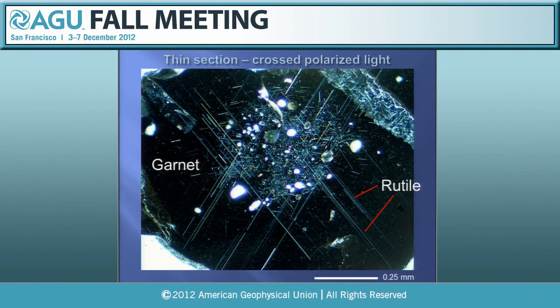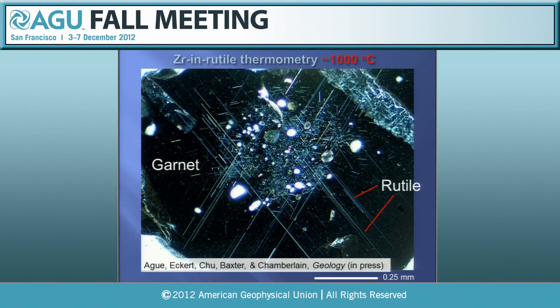Okay, it's known from experimental work that high titanium garnets really only form at very high temperatures and/or very high pressures, and the implication here is that these are precipitates that formed from the cooling garnet as the rocks were being exhumed. Okay, so if you do zirconium in rutile thermometry on these, we've used the Tompkins calibration, you get something like 1.5 weight% in some cases, ZrO2 in these rutiles, and that gives us temperatures of the order of 1,000 degrees centigrade. So this is a new ultra-high temperature terrain.